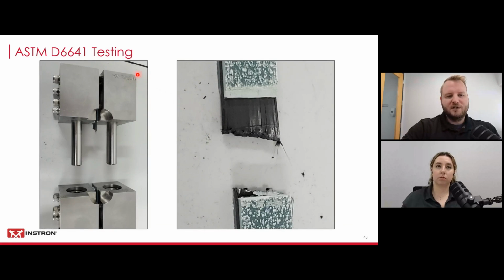On this picture now, you can see the fixture taken apart after the test. So the upper and lower part taken apart with the specimen still in place. And then I took the specimen out, and I wanted to give you a nice close-up picture of the failure location here, right where the tabs are ending within the free gauge section. And you can also see here the fixture basically making contact, gripping into those tabs. And that's certainly a lot of that compliance that we've seen in the video when the fixture is actually moving down, loading the specimen. The specimen failed around 45 kilonewtons. It's a unidirectional material.